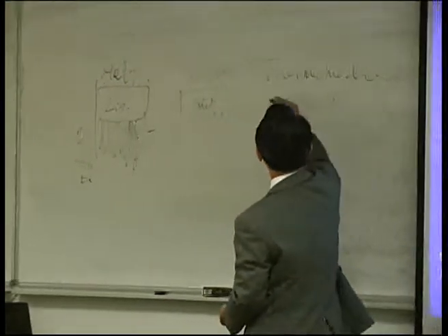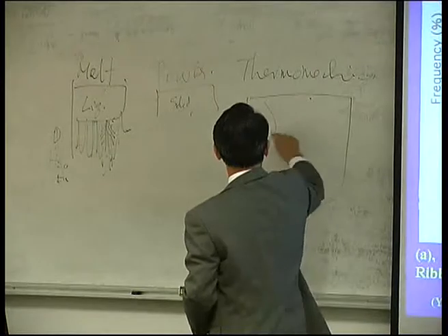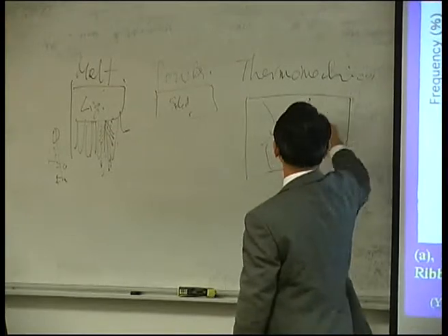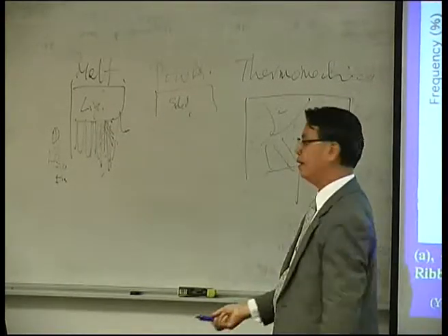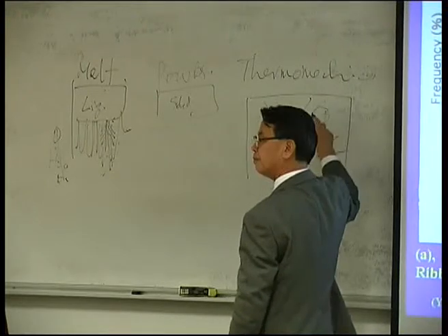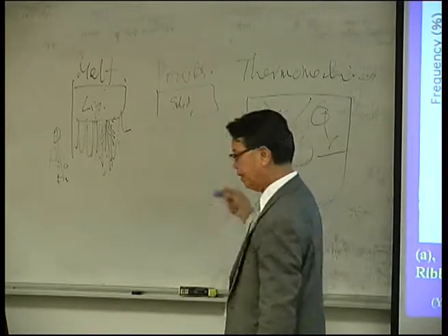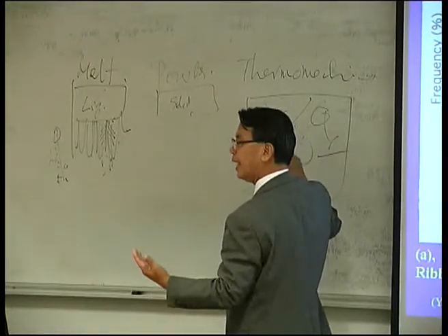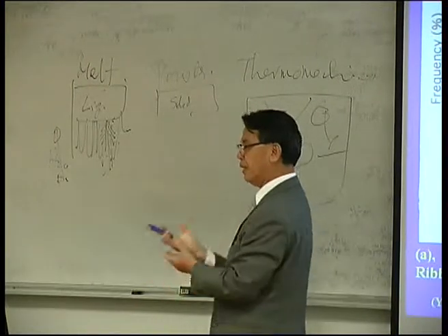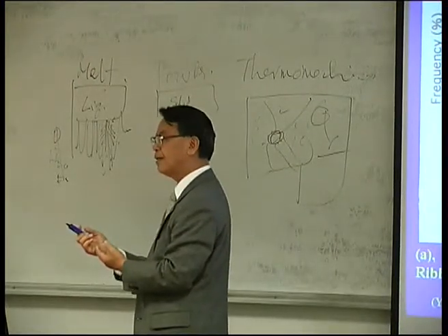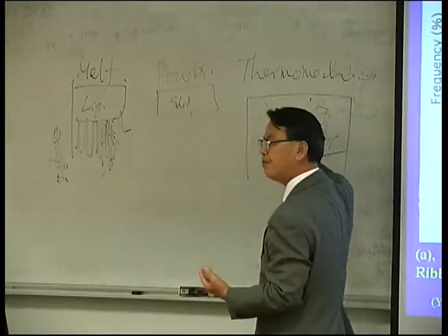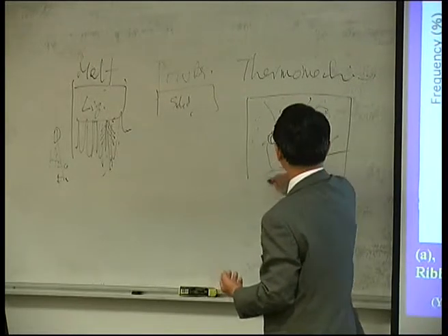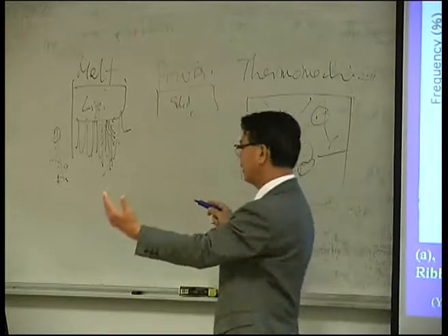Even in thermomechanical processing, if you deform the material, there are so many dislocations in the grain interior, but new grains have to form. In this case, over the last 20 years we already started to see that some specific high energy areas can be the site of new creation, premature new creation, because of the heterogeneity of stored energy, like this. So depending on the material or process, we can control the texture.